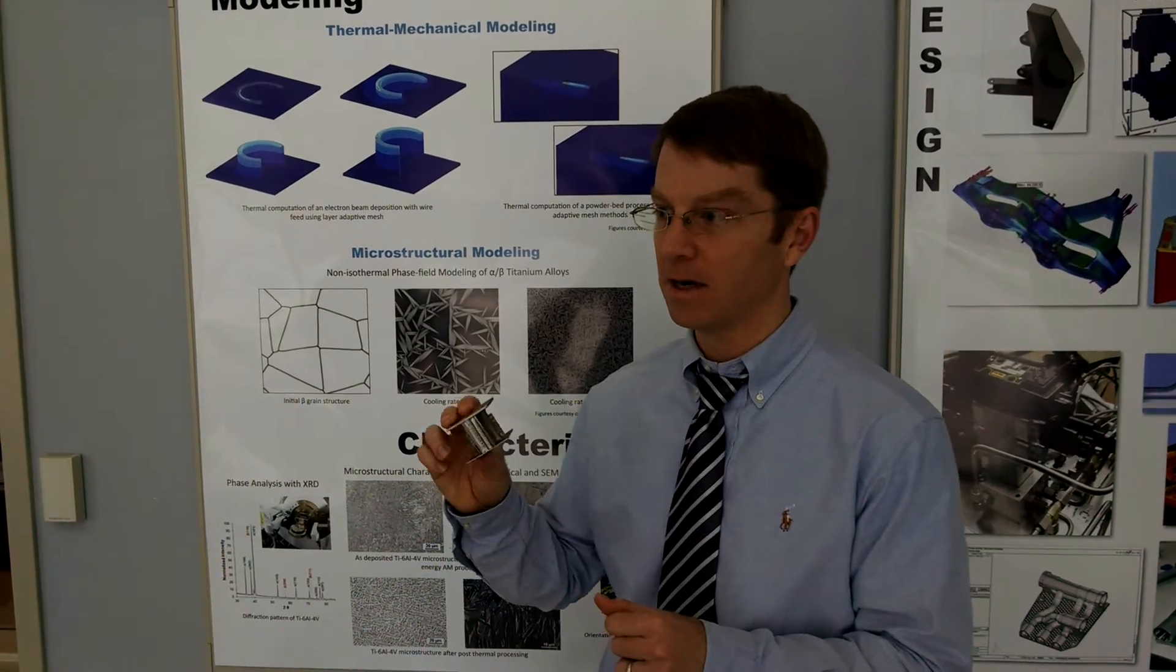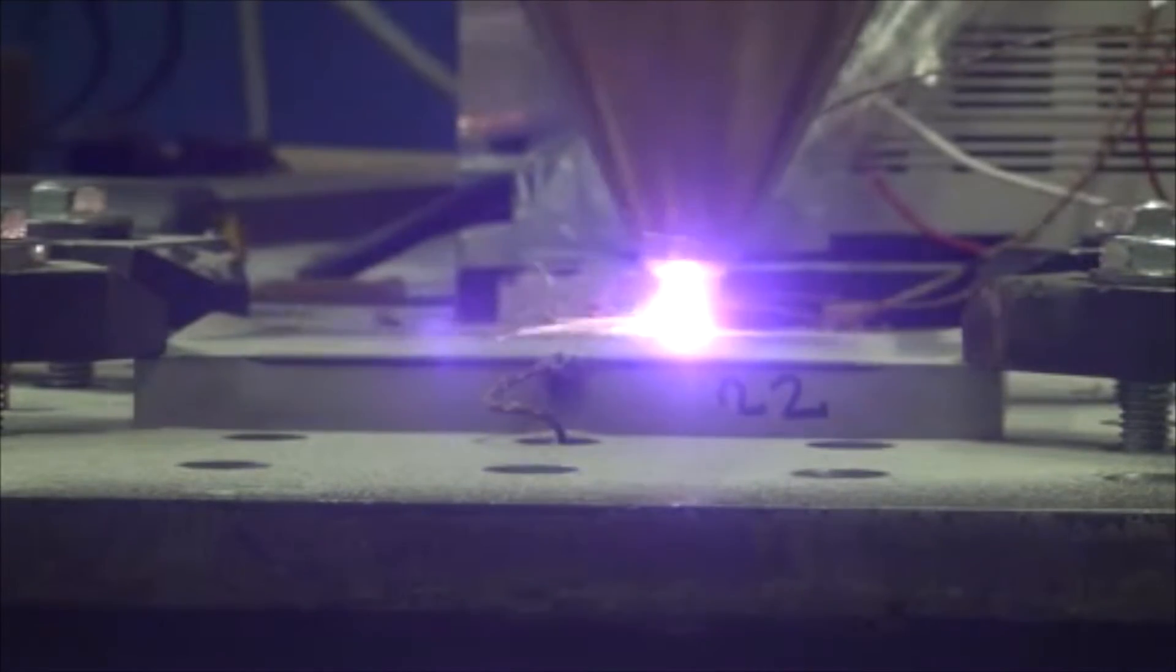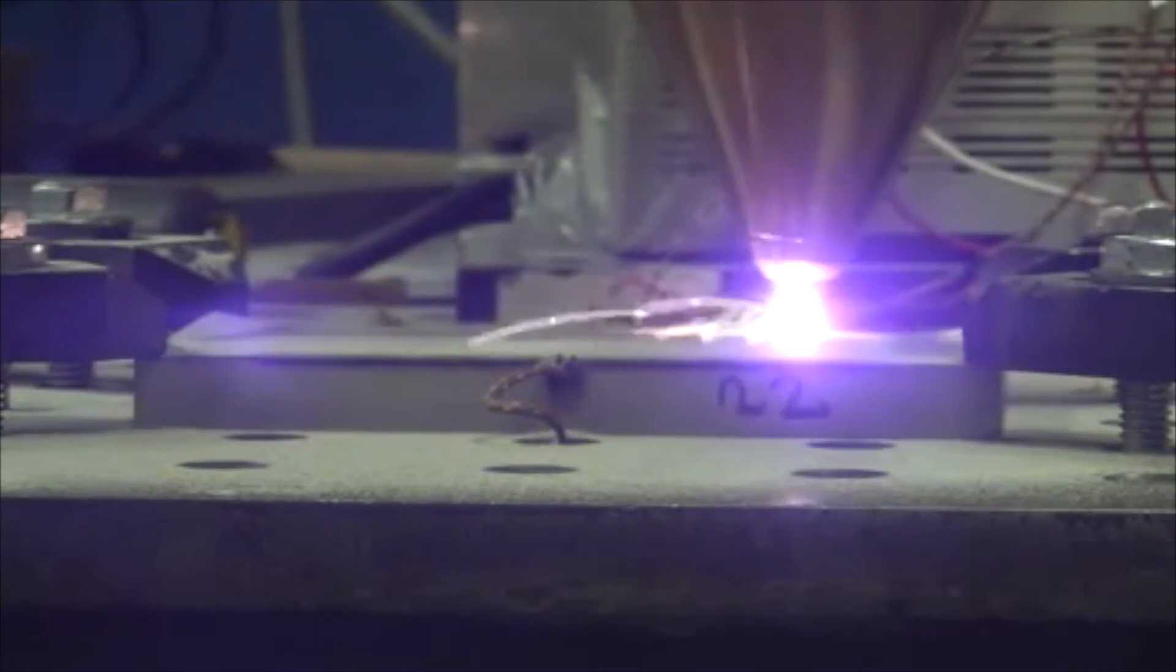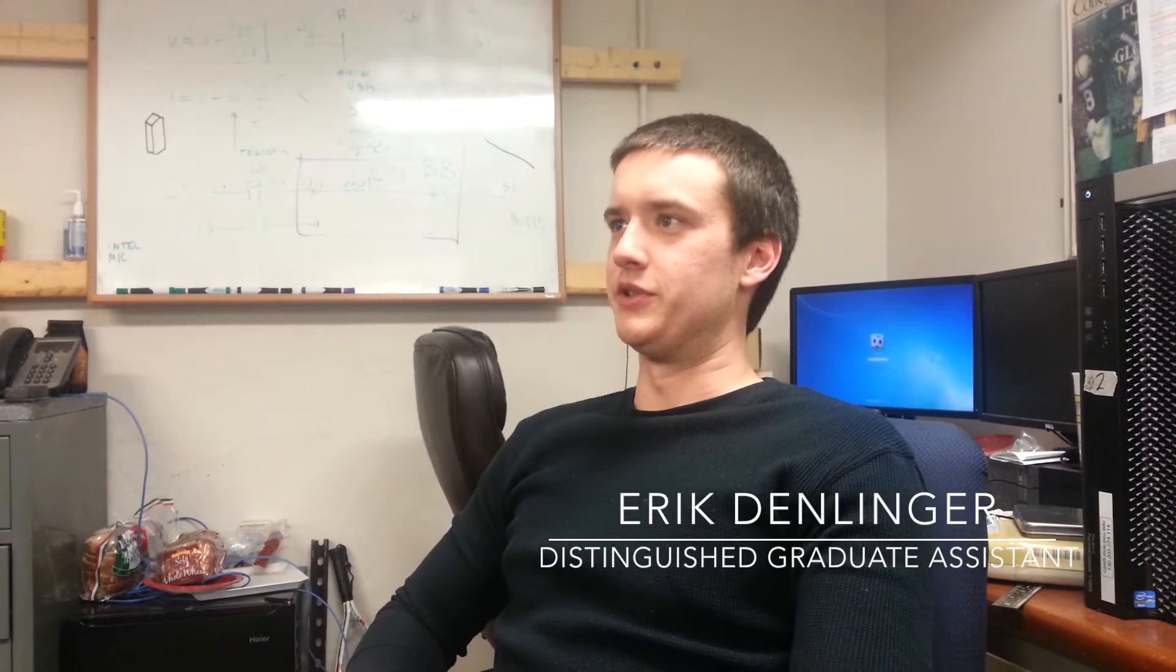We do thermomechanical modeling of additive manufacturing processes. So the biggest challenge, in my opinion, facing additive manufacturing is that during the deposition process, the laser or the electron beam causes large thermal gradients throughout the part. And these thermal gradients cause a buildup of residual stress, which in turn drives distortion. That distortion takes the part out of tolerance and can make it unusable.